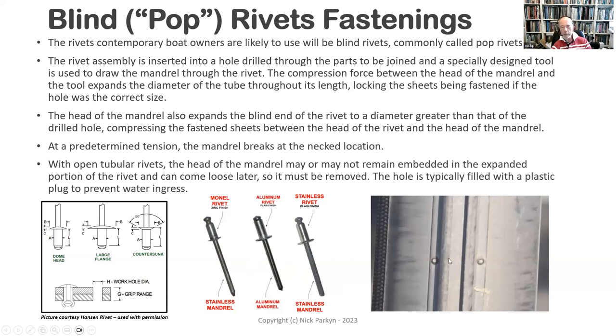Then we can also see here on the picture on the right-hand side that these rivet holes are filled with little plugs to make them watertight, obviously to prevent any water ingress into the spar itself, and to prevent any moisture inside causing corrosion. And these are little plastic plugs that you can actually tap in and then cut off flush with a very sharp blade. Or otherwise, the other option is just to fill those holes with some epoxy glue to seal them.